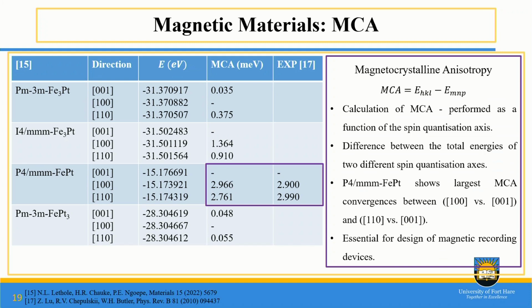Then when we optimize the structures along those directions, we determine the energies. The direction with the least energy, we call the easy axis direction, the direction where it is mostly magnetized. What we do is subtract the least energy from the other energies, and these are the values we find.